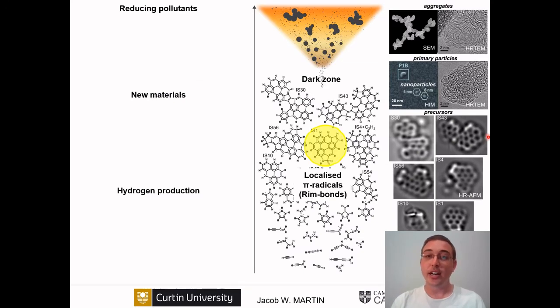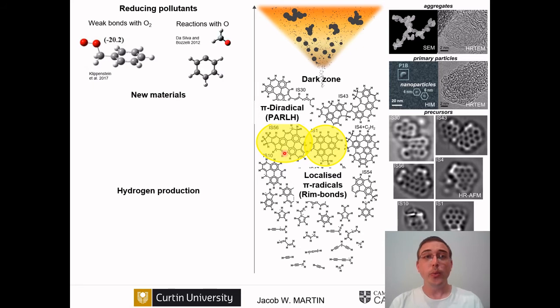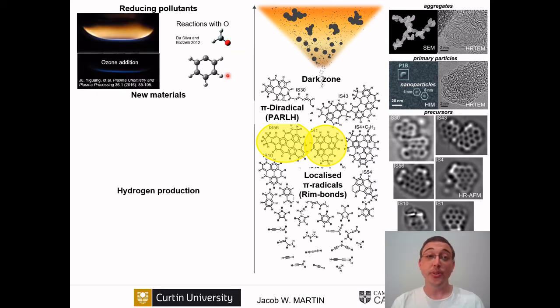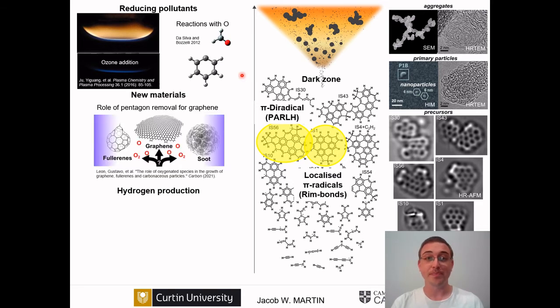So just in summary, I showed you these new reactive sites, these localized π-radicals that allow for diradicals to be stabilized within a single molecule and allow for polymerization reactions that we think are very promising for explaining soot. So what do we do with that? Well, we can't get rid of these sites with oxygen, but we can remove them with oxygen atoms. And one way to do that could be to add ozone to the flame. And we have seen that ozone addition to engines does significantly reduce soot.